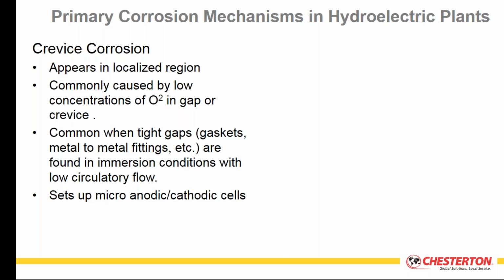Where are you going to see these gaps and crevices? You'll certainly see them in gasketed flange faces, metal-to-metal fittings. You may also see them in areas where you have stagnant flow, or no flow conditions. When you have those types of situations occurring, you'll set up very small micro anode-cathode cells, and that will also lead to a form of localized corrosion, but it's called crevice corrosion because it typically occurs in these regions which would be noted as crevices.